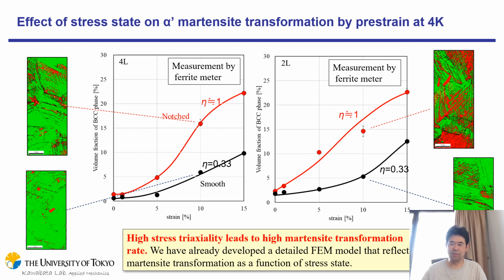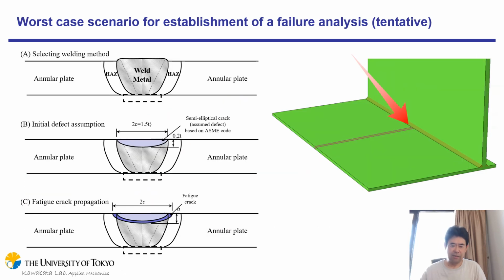This is important for judging continuous use after a huge earthquake, so we have to continue deep discussion of the mechanism. Now we are suggesting an appropriate failure scenario considering 316L's various properties. This is quite important for determining the criteria that must be required of the material. Firstly, we assume an initial defect perpendicular to the annular plate. Annular means the edge of the bottom plate, called the annular plate, and this side plate, the very bottom of the side plate. So this T-joint is a very dangerous part.